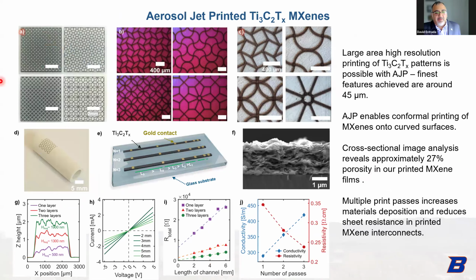Here's an example of some of the prints we can achieve with this ink on our Optomec 200. So this is just kind of a large area image. This is a 2mm scale bar showing, with the virtual design, you can print arbitrary patterns, high resolution. As we scale in or zoom in, you can see some of the finer features. We were able to achieve around 45 micron line width for these prints. So that's pretty good for printed 2D materials, right? You can push down to about 10 microns, but you get a lot of overspray.